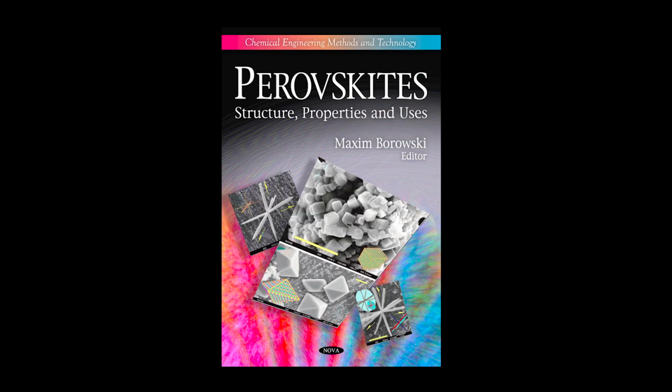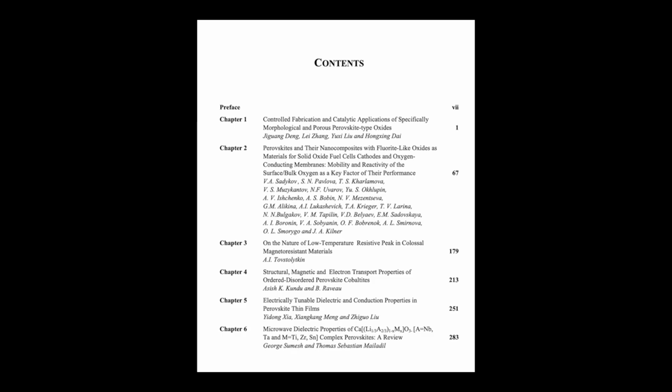Let's compare the manganites versus the ferrites and cobaltites. For manganites, where B is manganese, Mn, under the relatively high PO2 conditions typical of an air-side SOFC cathode, the material strongly prefers to compensate for the charge difference introduced by the A-site dopant, like Sr2+ replacing La3+, electronically. It does this mostly by oxidizing some Mn3+ ions to Mn4+ ions, creating electron holes rather than ionically by creating lots of oxygen vacancies. They tend to exist in a thermodynamic region where the oxygen vacancy concentration is kept quite low. The energy cost to pull an oxygen out of the stable Mn-O lattice is just too high under those conditions. So they're generally poor ionic conductors compared to the others.